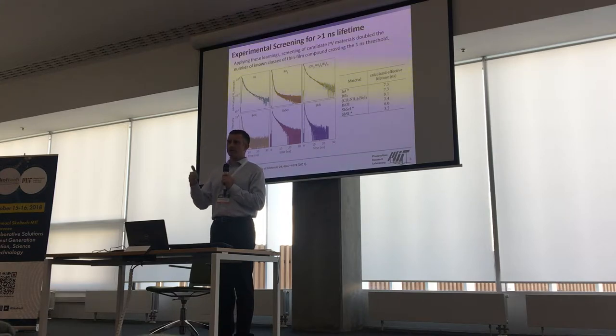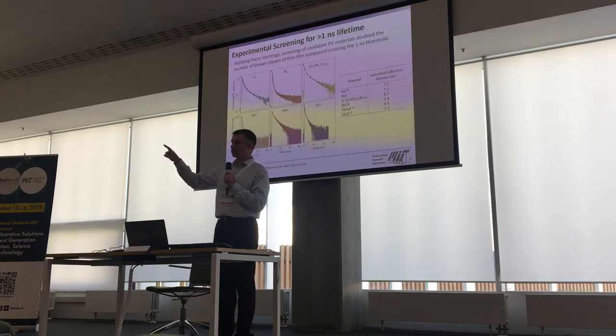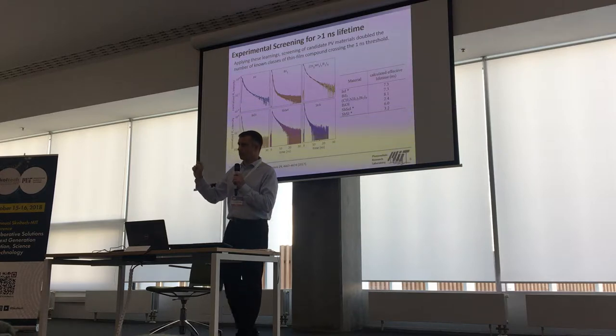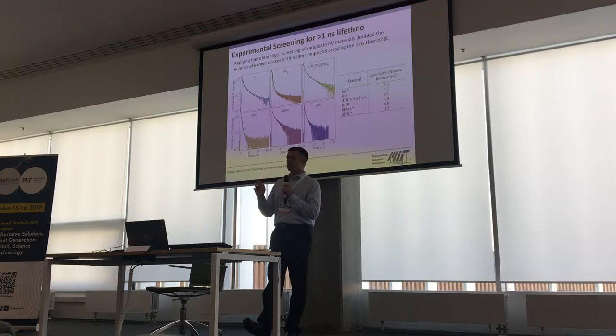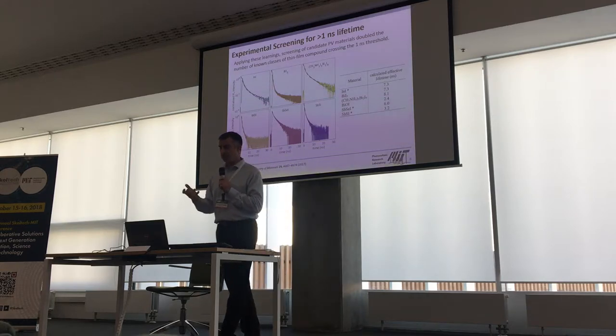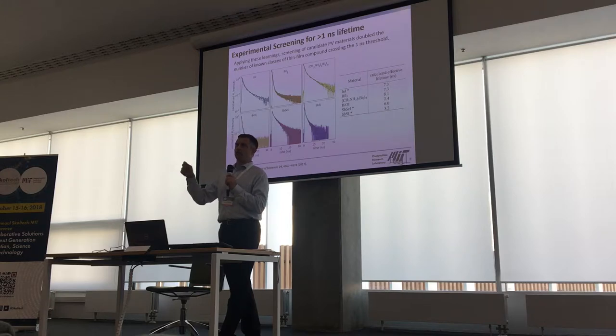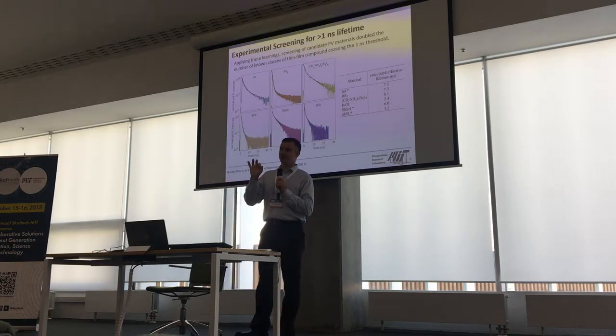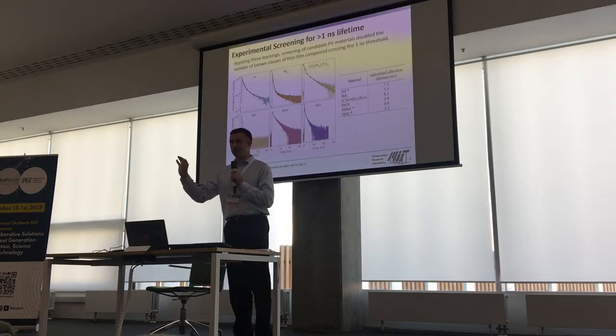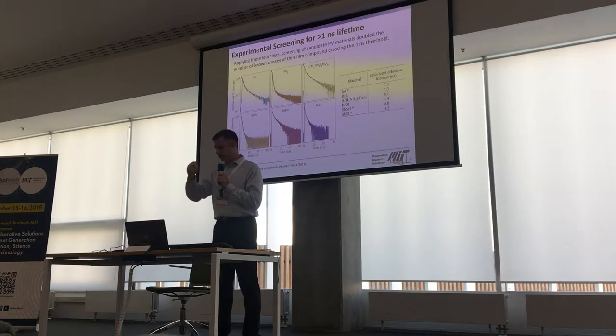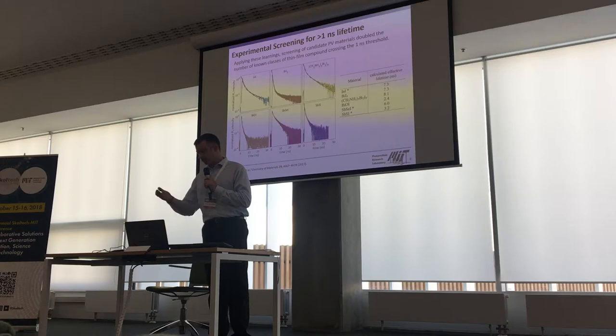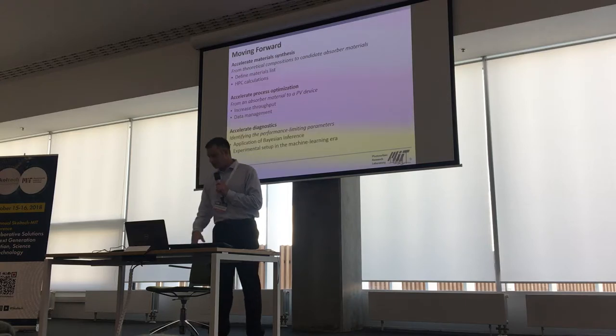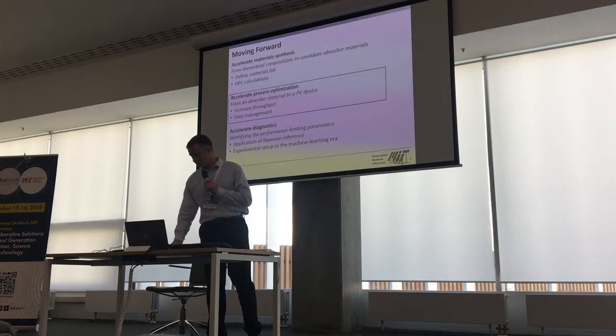And this is a problem in 2 ways. Number one, it's difficult to validate the theory. So it's difficult to push information back to theory that can help refine it, right? So the inverse design paradigm will only be, shall we say, accepted universally once the theory refines itself to the point where its predictive capacity is exceptional. And it cannot reach that point until the experimental throughput catches up and validates or refutes theory at different points so it can refine itself in its predictive capacity. And secondly, from the obvious point of view, we need to increase our throughput so we can actually get a working solar cell. So it brings us to the next point, which is accelerating process optimization.